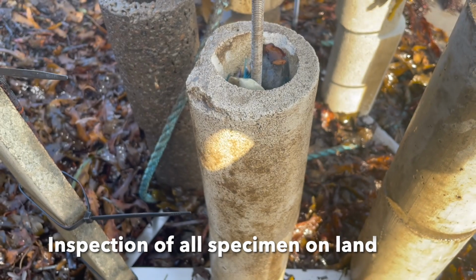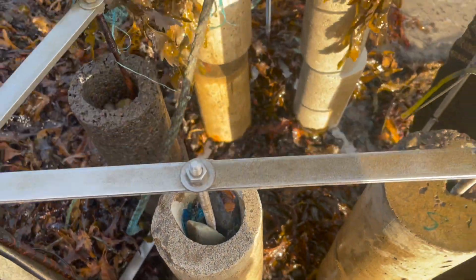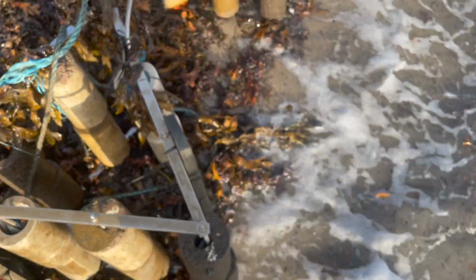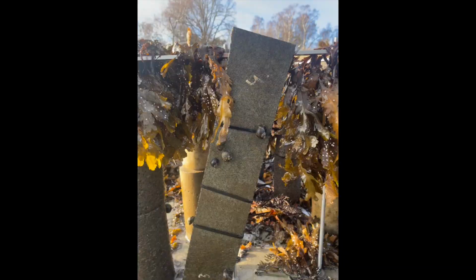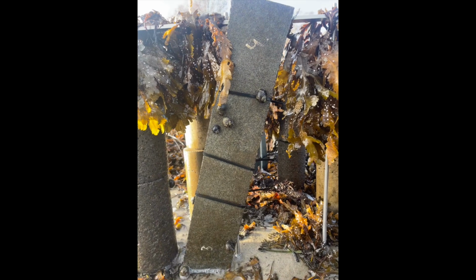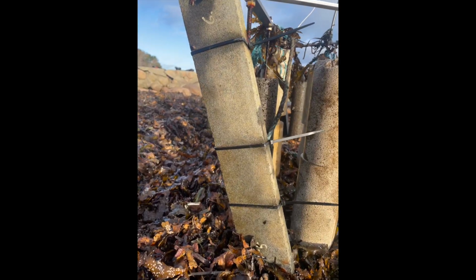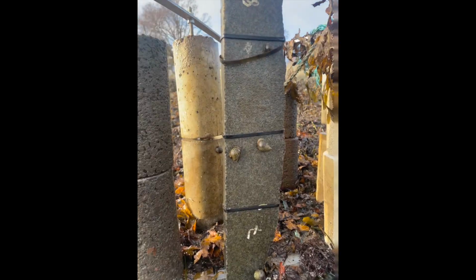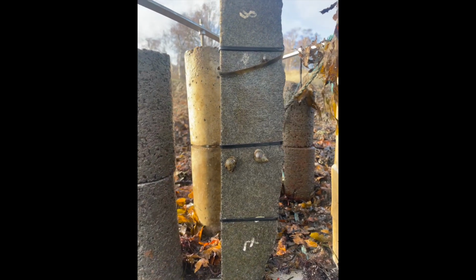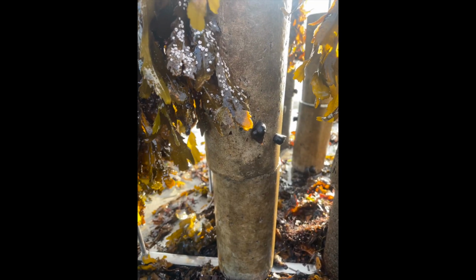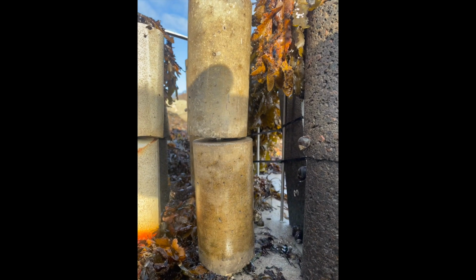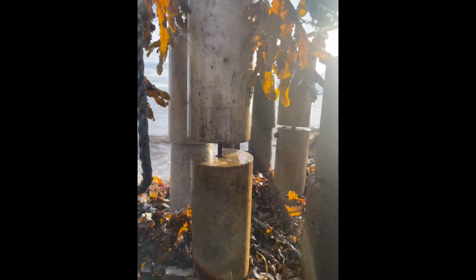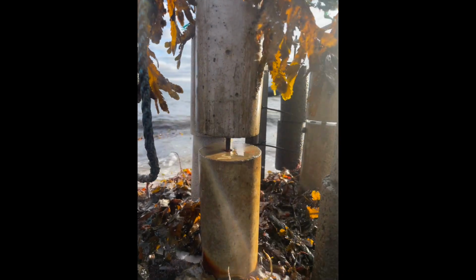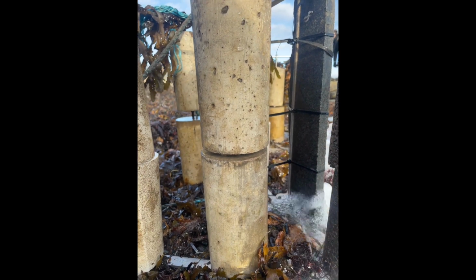It was noted that all specimens suffered a decline in algal growth, possibly due to the seasonal changes or to severe winter storms. Granite samples were seemingly bare of all algal growth, but had the most abundance of snails. This preference could stem from a chemical composition of the natural granite. The construction concrete fared the second best, with some algal growth left, but its smooth surfaces proved too slippery for the algae to hold on to.